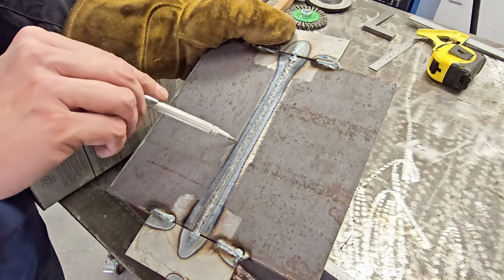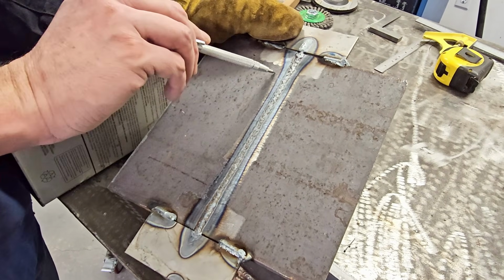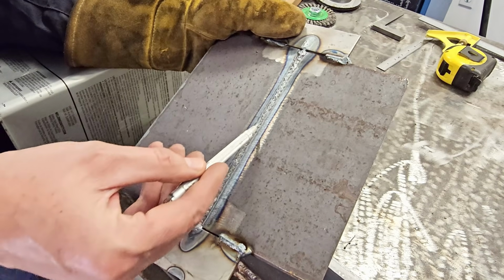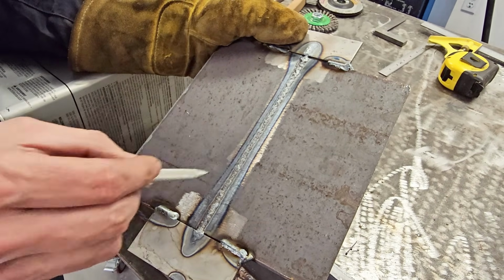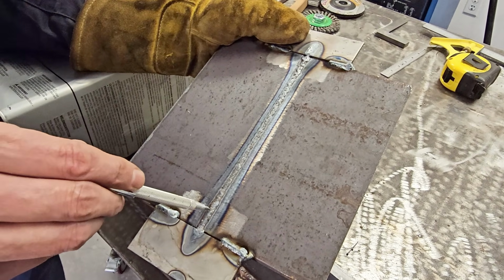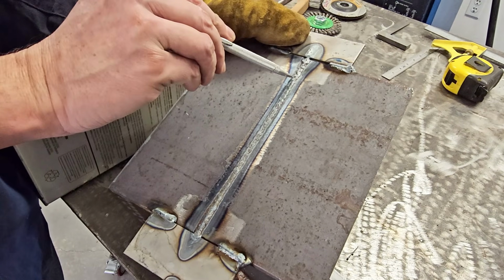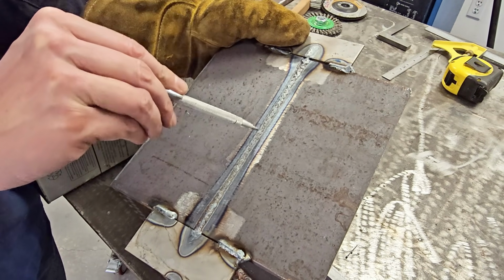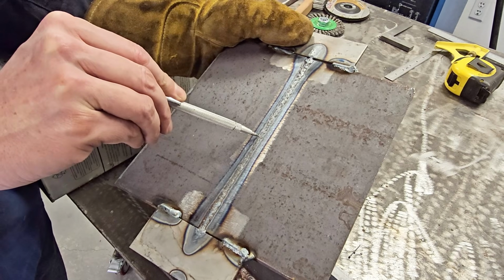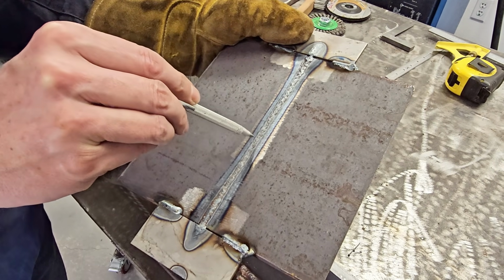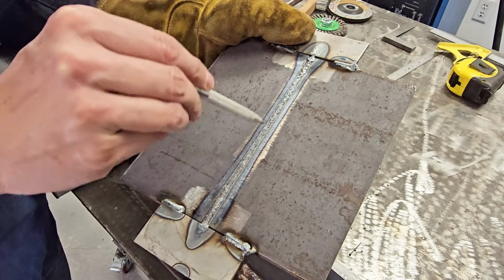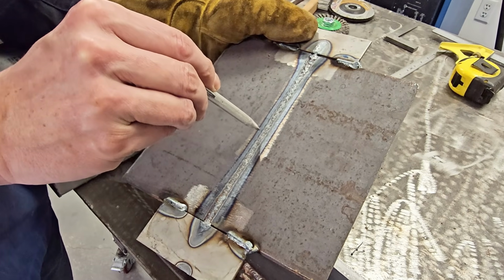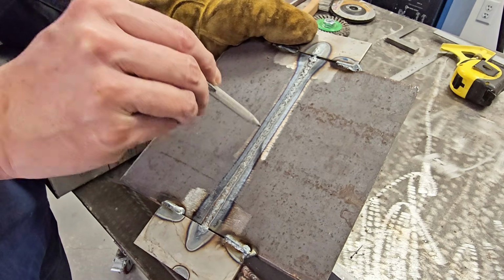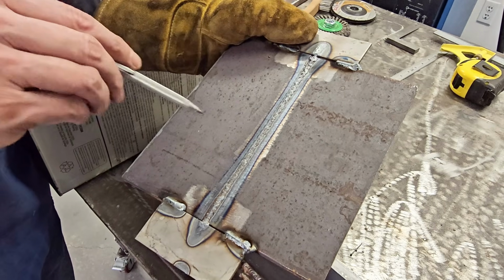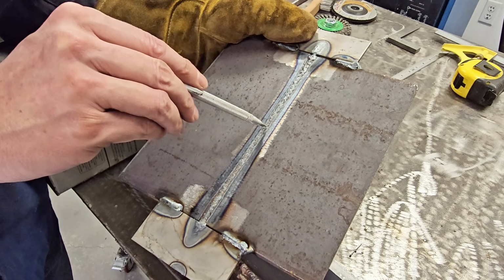Okay, so here's the root side of my plate. And you can see that I got full penetration all the way through. I had a little variation in my root opening. You can see on these ends it was more open, so I got more penetration. And in the middle it got pretty tight. So I really had to focus in this portion right in the center and try to keep my heat right in the center of that root opening to get it to penetrate through.